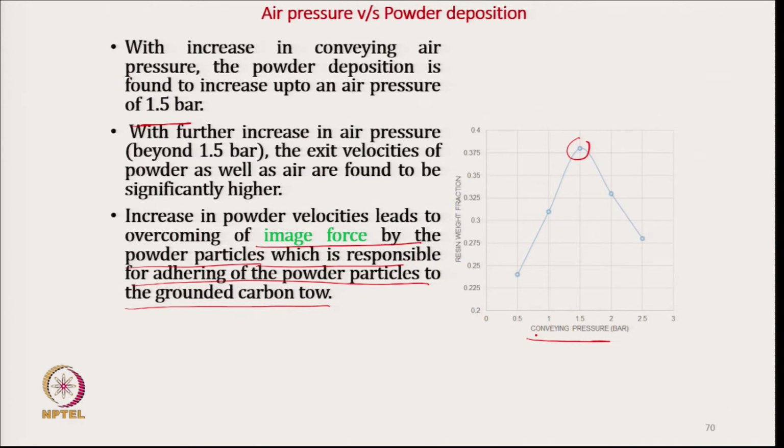but if we increase further beyond 1.5 bar, then it will try to overcome the image force of the powder particle. So, if powder comes at very high speed, high pressure, it will overcome the adhering force and the powder will move beyond that, will be separated.